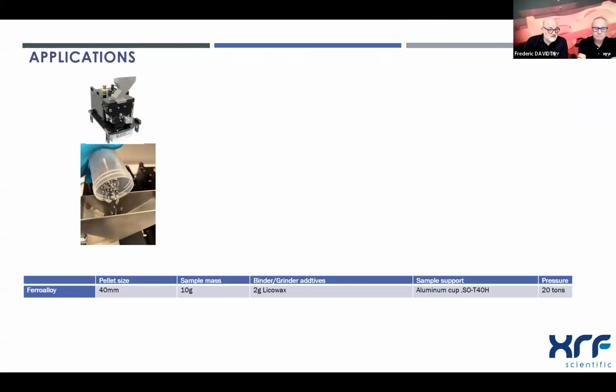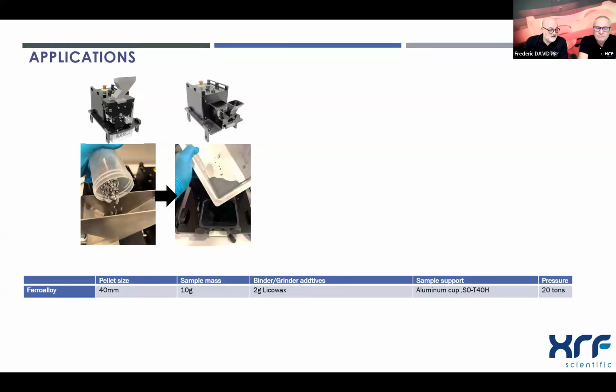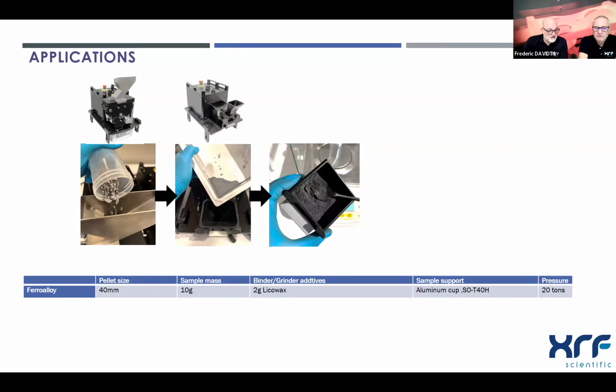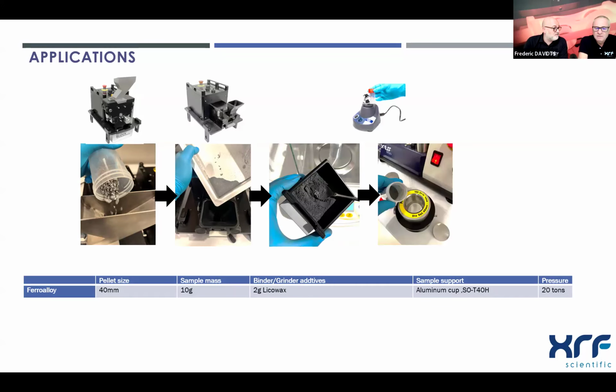Here, another application, ferroalloy, ferrosilicium. In this case, we have received granules that we crush in a mini grinder, mini crusher. Then we grind to obtain a fine powder below 75 micron. Then we take 10 grams of this fine powder. We mix it with wax, Licowax, 2 grams.